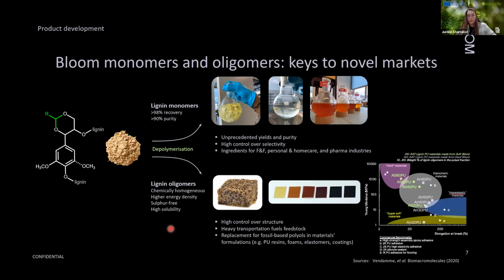And those are really interesting compounds because they have a lignin-like structure, but they have a higher energy density that could allow us to use them as transportation fuels, for example. And also they have a high solubility. This is really different from the lignin itself. And with that, we are able to use them as a replacement for fossil-based polyol for some materials. So mostly polyurethane compounds. So we could use them to make a polyurethane foam with a high oligomer content, and also polyurethane elastomers. Also, by varying the oligomer content in those, we can see that we could really shift the properties, but still most of them were falling into the range of elastomeric materials due to the good elongation at break and Young's modulus.